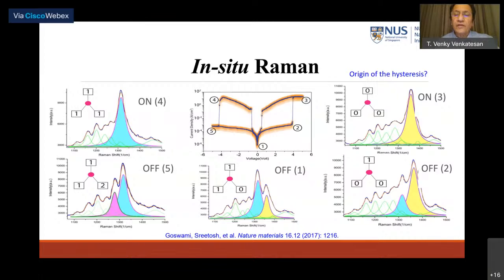For example, if they're in 0 0 0, the LUMO bands, or what in condensed matter we'll call the conduction band, of the molecules all line up because they're identical states. So it's very easy for the electron to hop from molecule to molecule. But when one of the ligands is dissimilar, then the hopping probability from this molecule to a similar 1 0 0 molecule will be roughly 2/3 that of the